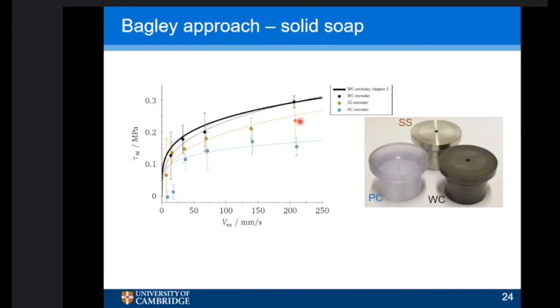And the question is, what's the temperature of the material at the wall as a result of it being sheared? Because it will do that work against itself. And the polycarbonate, of course, is actually a very good insulator. So that means all the heat stays in the material. Whereas the stainless steel and the carbide are much better conductors, so they will take the heat away. And you don't need a big change in temperature to change the rheology of something like soap. I might have answered that question already.